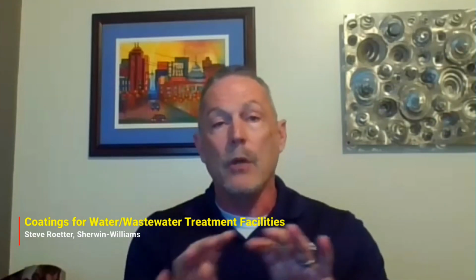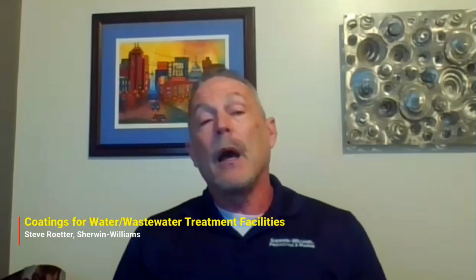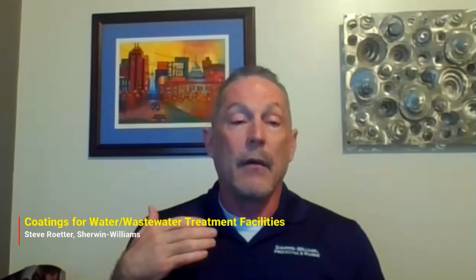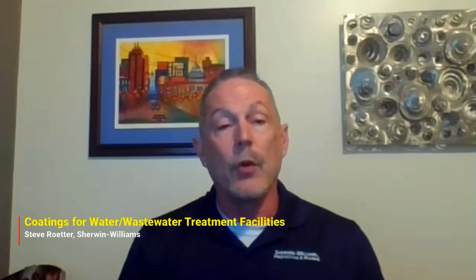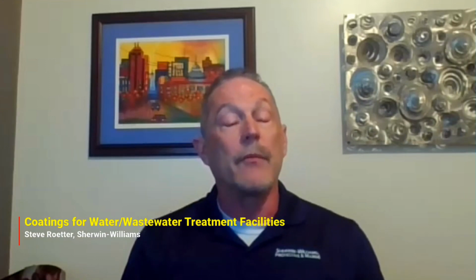So we deal with the outgassing in two different ways. Number one is with a primer sealer that we would put over the surface of the concrete that penetrates the concrete pores and seals it up before we come back with 100% solids material. The other thing you'll see contractors do, and I even have seen it specified, is only applying coating to the surface of the concrete during the late afternoon, early evening hours when temperatures are decreasing and the concrete is in its breathing in mode, and you'll get far fewer outgassing problems that way.